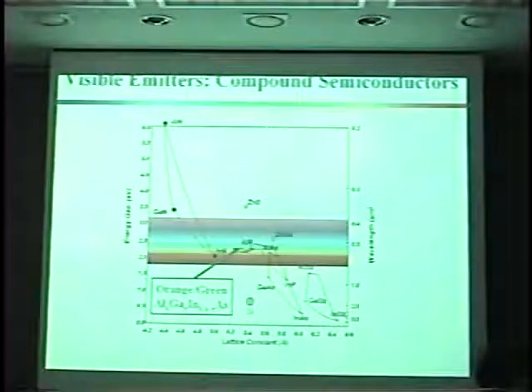And it wasn't until around 1992 when Shuji Nakamura came along and demonstrated that gallium indium nitride, an active layer of a composition somewhere around here, could get very efficient blue emission by forming a solid solution between gallium nitride and indium nitride. So with the advent of the gallium nitride based blue LED, we had the red, green, blue combination, and as a result we have the possibility for an LED display.